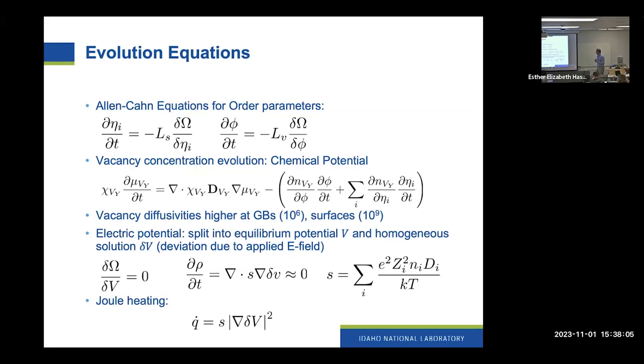We split the electric potential into the equilibrium potential, which derives from the grand potential functional, and the homogeneous solution, which is due to deviation of that potential due to an applied electric field. And then we calculate the electrical conductivity based on the defect densities and diffusivities. And then Joule heating is based on the homogeneous field magnitude